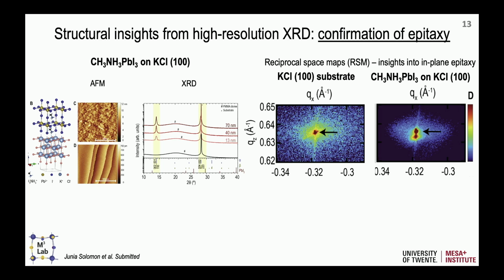So this is a little bit of a summary. I will not go too much in detail, but this is how the single crystal of potassium chloride will look after cleaving. So you can see atomic steps, and then you put the MAPI, and it looks like that. Now, it looks a little bit grainy, so you say, okay, is it really epitaxial or not? In X-ray diffraction, you see it is single-oriented in the 001 orientation. But again, here we cannot say much about epitaxy, but to confirm, we do reciprocal space maps.